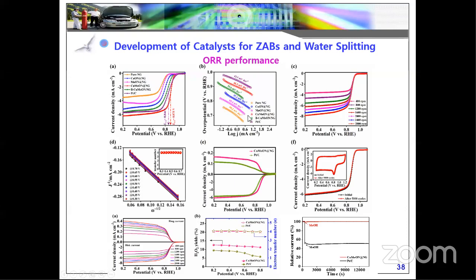And the Tafel plots confirm the value of the materials: the copper molybdenum is lower compared to the monometallic counterparts, and the platinum carbon materials are almost similar. We also ran the LSV of the catalyst at different speeds, in the oxygen atmosphere. When increasing the speed rates, the current increases towards the negative region. And from this current, we also calculate the KL plots. From the KL plots, we confirm our material shows 4-electron transport kinetics, because 4-electron achievement is very important for ORR. And all these performances are measured by the RDE, the rotating disc electrode, but the RDE alone is not a confirmation study.